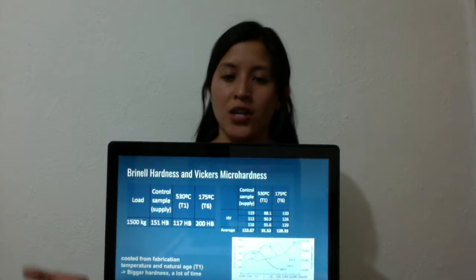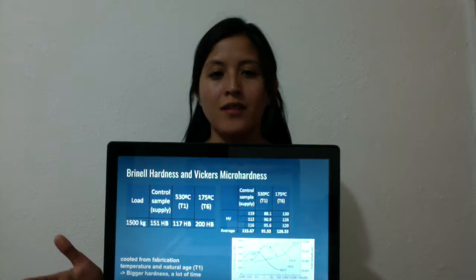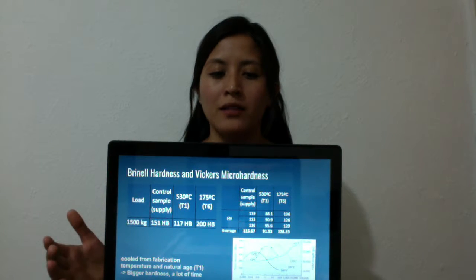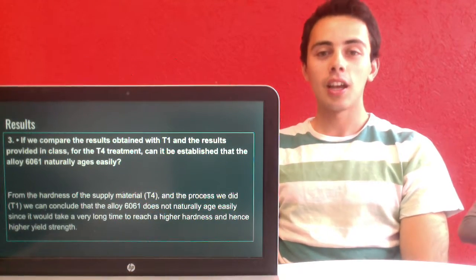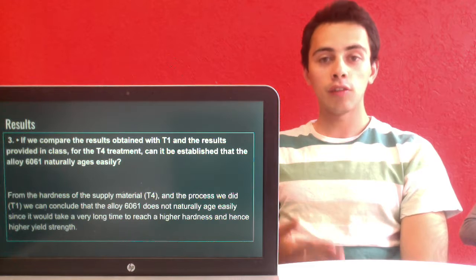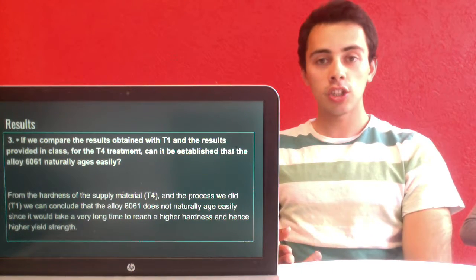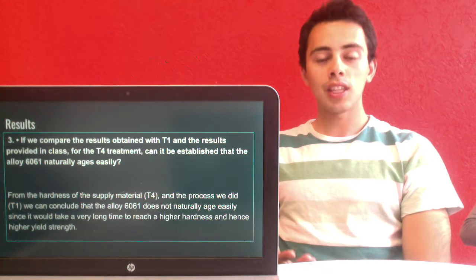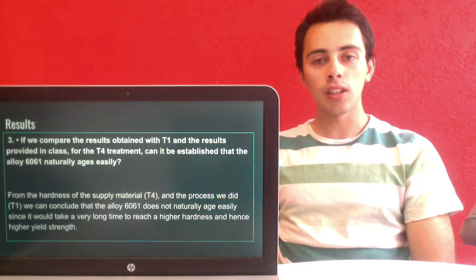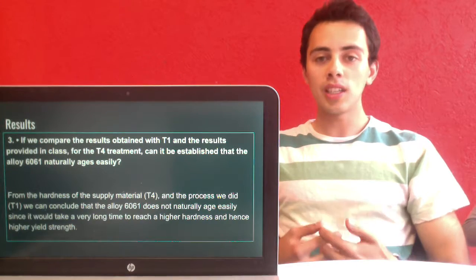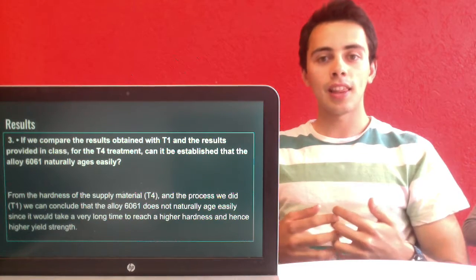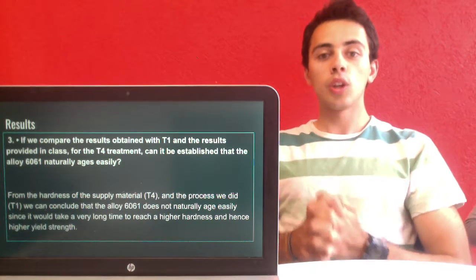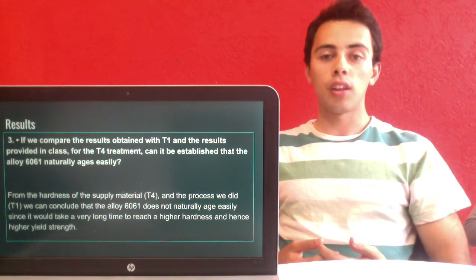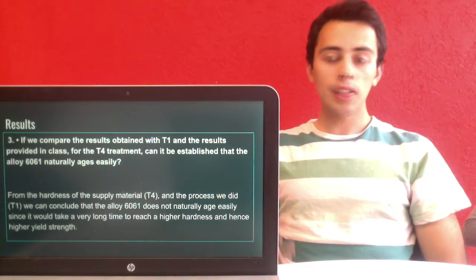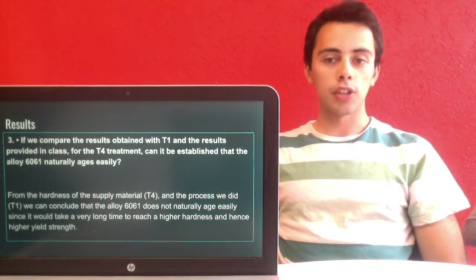So we can see a change in the hardness that tells us that the sample has the T1 heat treatment applied successfully. From the results obtained in the practice, assuming that the supply material has a T4 treatment and the second procedure is T1, we can conclude that this aluminum alloy does not age easily, because in the T1 that we did, we had a lower hardness than the original T4 supply material. So it would take a really long time for natural aging to increase the aluminum's hardness and its yield strength.